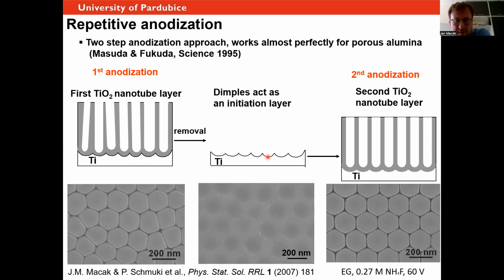have these dimples in the titanium surface imprinted. And then when you continue the same thing, you can actually get much higher degree of ordering. So you see you have more or less ideal hexagonal packing of the tubes. Everywhere there is not really big defects.